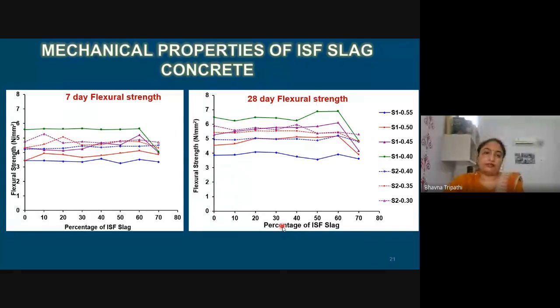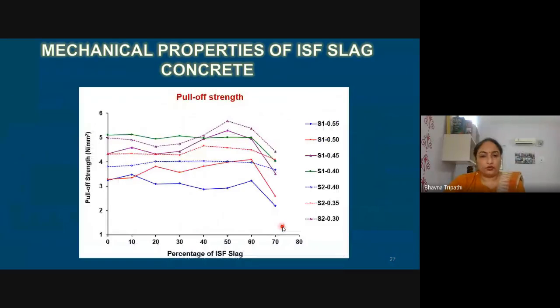Flexural strength is very much dependent on the paste quality, and the flexibility of the mix is also very closely related to the paste characteristics. Again, the pull-off strength, which denotes the strength of the cover zone concrete, also showed that the 70% ISF slag samples are having a significant decrease in comparison to control. So largely we can say that compressive strength is okay, but the flexural and pull-off strength do not recommend use of ISF slag more than 60%. And if we are able to compensate and design a mix with proper paste content, then this deficiency can also be overcome.